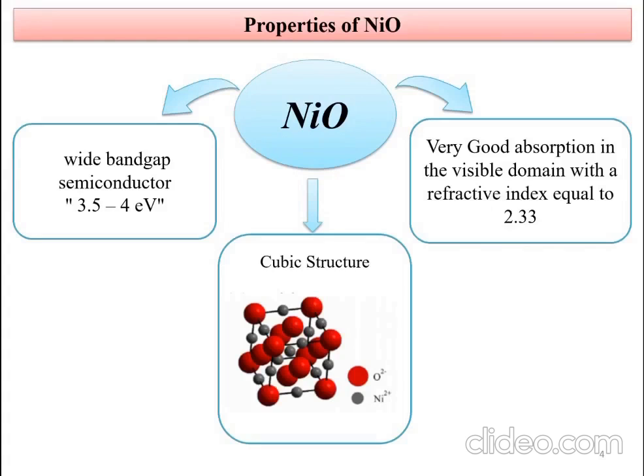First, we will present the nickel oxide properties regarding its band gap, which is between 3.5 and 4 electron volts. Furthermore, we selected nickel oxide for its absorption in the visible region, with a refractive index equal to 2.33. Finally, nickel oxide has a cubic structure like an NaCl molecule.